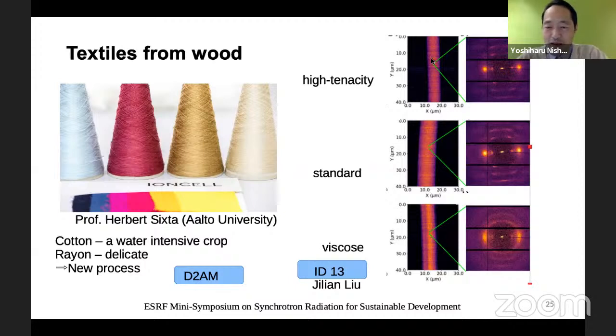And this is a micro diffraction analysis being done at ID13 by Jilian Liu. This is a scan of the sample, and each pixel corresponds to one diffraction pattern like this. And here he is comparing high tenacity fiber from the new process, standard fiber from the process, and the viscose, the classical regenerated cellulose fiber. Here we see different types of ordering and microstructure inside the fiber. And what we want to understand is why this new process is leading to higher mechanical property, especially in a wet state.